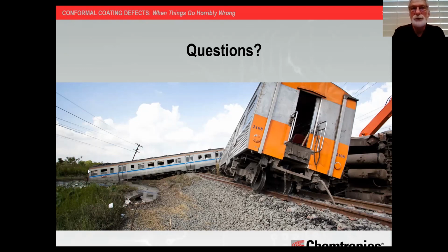Well, if you have dendritic growth underneath a coating, that means that you had some ionic residue there. My apologies, I was thinking of tin whiskers. So dendrites. Okay, my apologies. Let me clarify, I was talking tin whiskers, totally different subject. Dendrites grow from ionic residues and form branch structures from flux residues. I'm sorry. Please continue, Pierce.